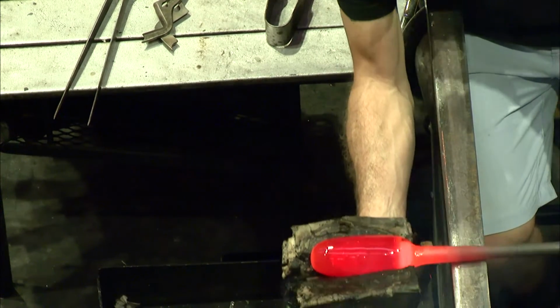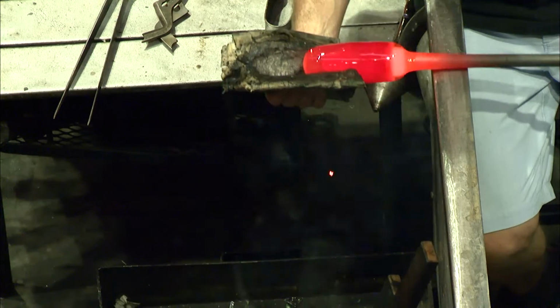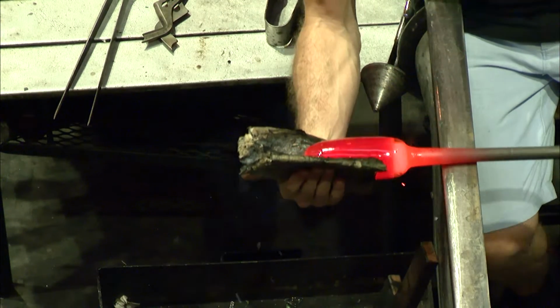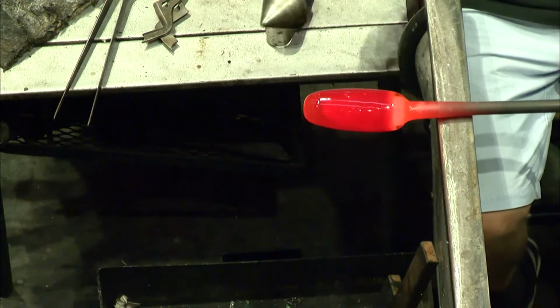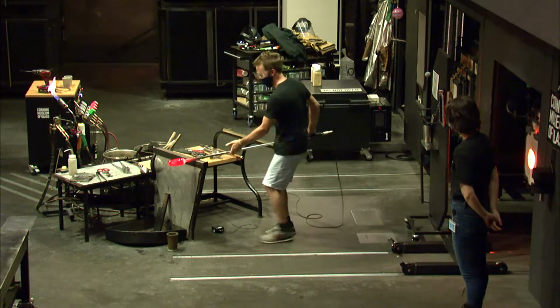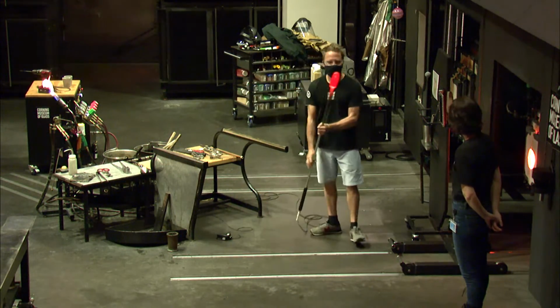This is really important. If you don't do that correctly, you can go into that melting furnace, plunge your starter bubble, color or not, below that molten surface, and start turning, and it heats up way too fast and just starts drawing off the end of the iron and contaminating your pot of molten glass. So that is a really important step in that process of building up the material you want to create the piece you want, which is another thing that comes with time.